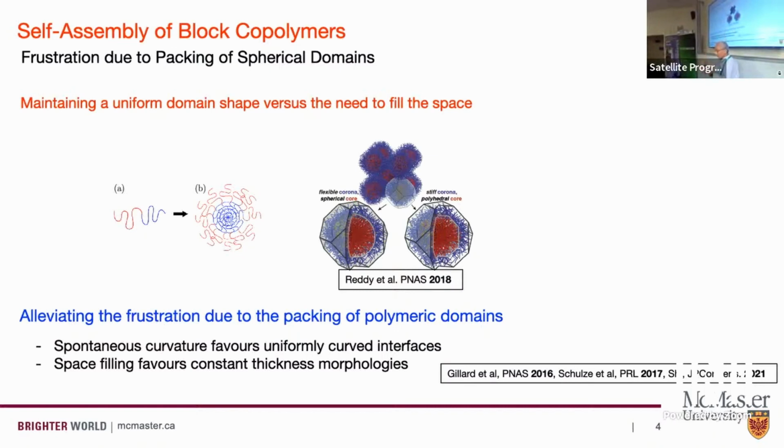But of course, what that does is it breaks the rotational symmetry from one micelle's point of view. Now you have a lattice. The polymer will need to stretch out to fill the space, or in other words, the packing density is always 1. You always fill the space. Polymers don't like to have voids.